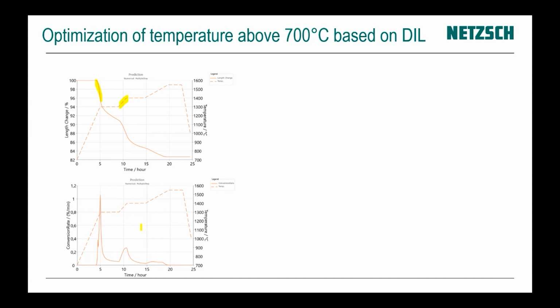For this non-optimized temperature profile, we can calculate a first derivative and see that somewhere here the shrinkage is very fast. The shrinkage rate is very fast. And it means that for a very fast shrinkage rate, we have some mechanical stresses. And the process can produce some cracks in the material exactly at this point. And in order to improve the quality of the material, we must reduce the heating at this position in order to make this shrinkage rate a little bit slower.